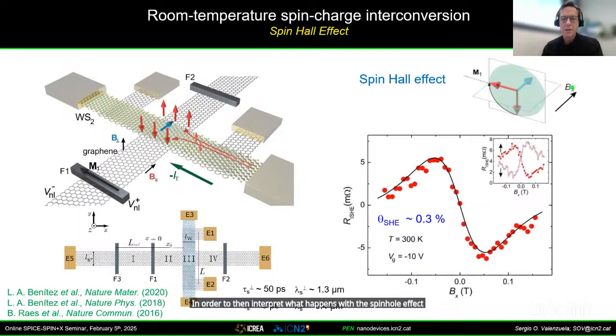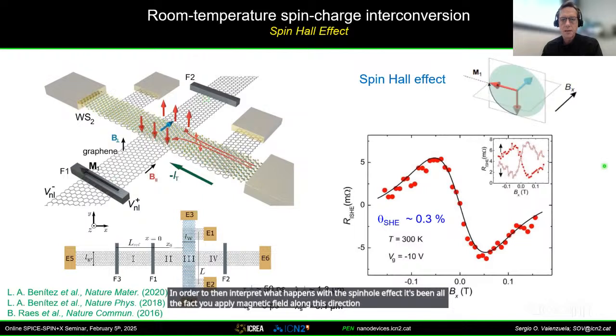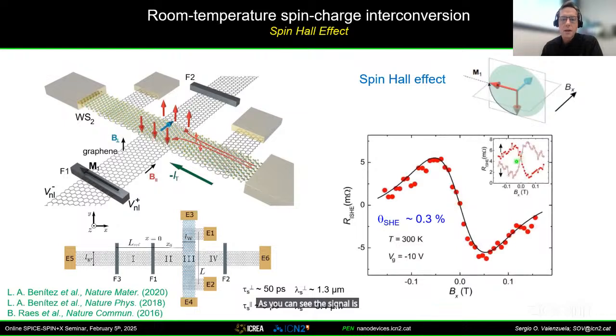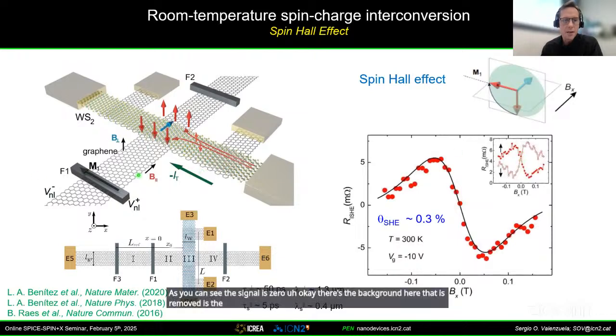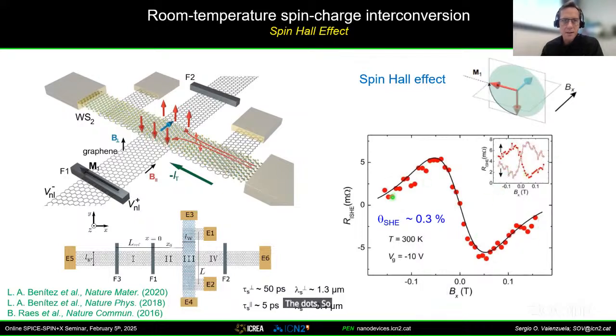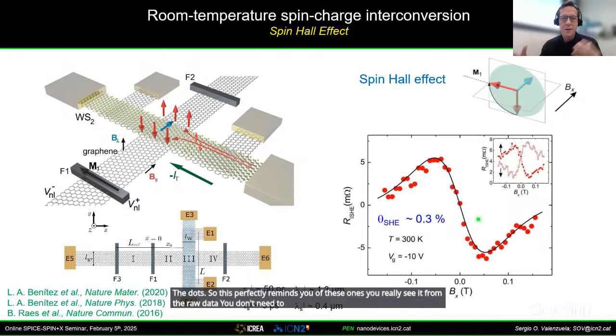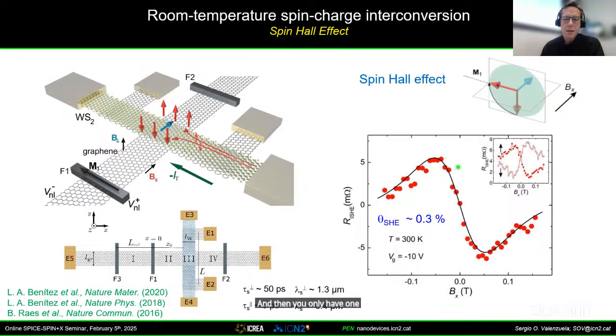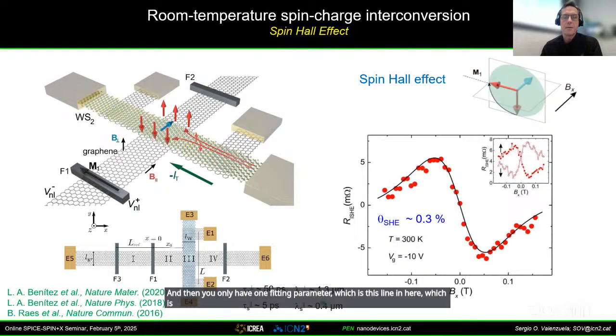The spin Hall effect: you apply a magnetic field along this direction, so that the spin precesses. As you can see, the signal is zero. Okay, there's the background here that is removed, but it coincides for the orientation in this direction and the opposite of the magnetization. And then when you take the difference, you obtain this signal here, the dots. So this perfectly reminds you of this one. So you really see it from the raw data. You don't need to take a difference of two different curves that give you something. And then you only have one fitting parameter, which is this line in here, which is the spin Hall angle, because the other parameters you know.